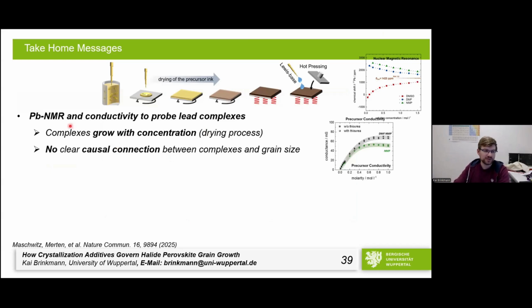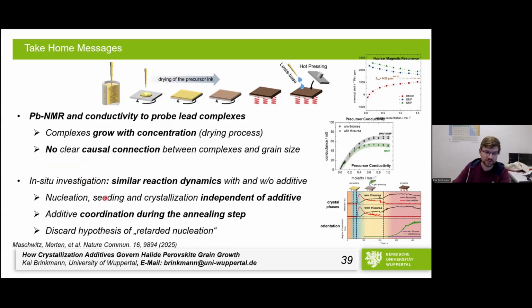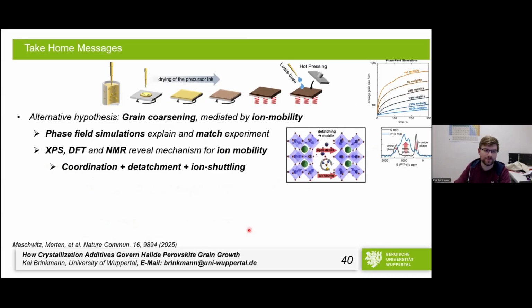So what did we do? We probed the precursors and the complexes. We can probe them very nicely. And the problem is that the causal connection for the additives in the lead complexes was basically not existing. The in situ investigations then told us that the reaction dynamics are roughly the same with and without additives, during the nucleation and during the perovskite formation, and just the annealing step is very, very important. And this is basically the part when we discarded the retarded nucleation hypothesis and eventually came up with the explanation that apparently, at least for the halides, or at least the iodine-containing lead perovskites, I would say, which are most important for all the solar cells, we have grain coarsening that is mediated by the ion mobility.